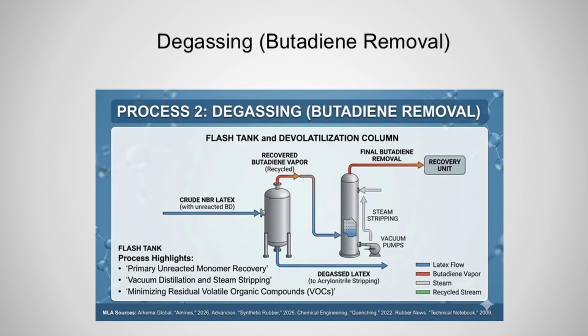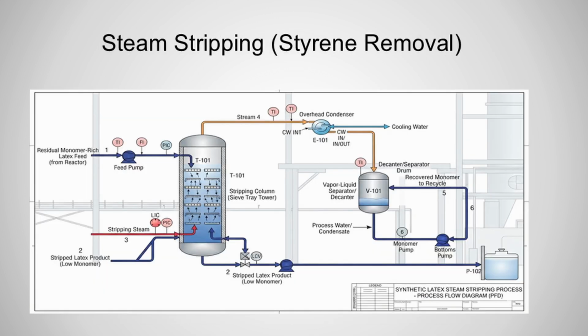Degassing. Butadiene removal. The unreacted, highly volatile butadiene gas is flashed off under reduced pressure and captured for recycling. Steam stripping, styrene removal. The mixture is sent to a stripping column where steam is injected. The steam vaporizes the remaining unreacted styrene monomer, separating it from the latex so it can be condensed and reused.